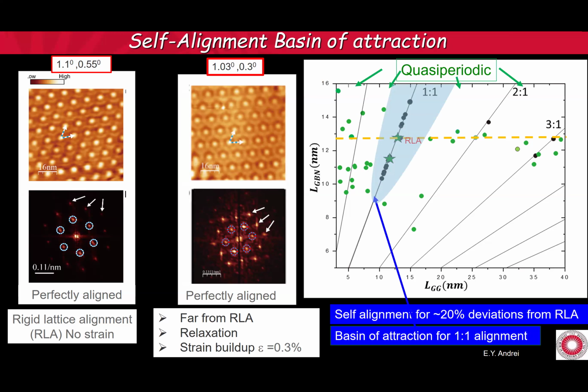So you can be as far as 20% from the rigid lattice alignment and still be 1-to-1 aligned. And that's why we think it was possible to see it with transport, because there was this alignment, this relaxation effect. Now let's talk about the points that are off the 1-to-1 alignment. Those are not a periodic crystal. They're a quasi-periodic crystal.